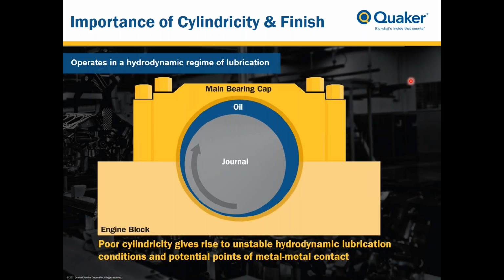It is pretty well accepted and known that this process, the separation and lubrication of the journal from the bearings, operates under predominantly a hydrodynamic regime of lubrication. The oil that separates these two parts as the journal is rotating is formed as the lubricant is pressurized between the journal and the journal bearing, and it establishes a film of a certain thickness. The film thickness that is needed and reported in the literature to sustain a good separation in this operation is down at 2 micron thickness, and sometimes can even go down to 0.5 micron in lubricant film thickness. This thin a film is needed to maintain a good separation between the journal and the journal bearings.